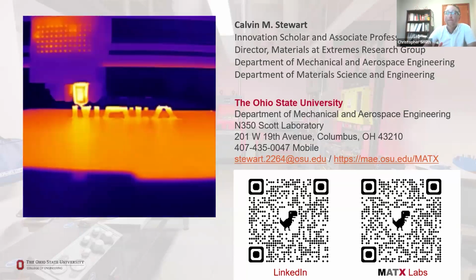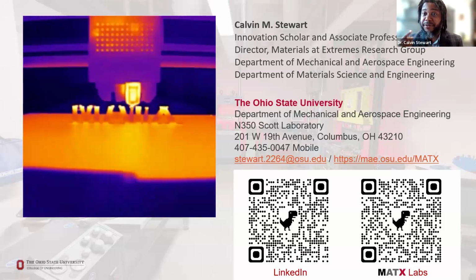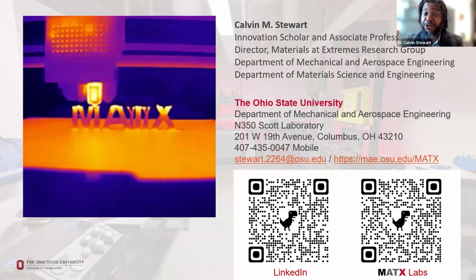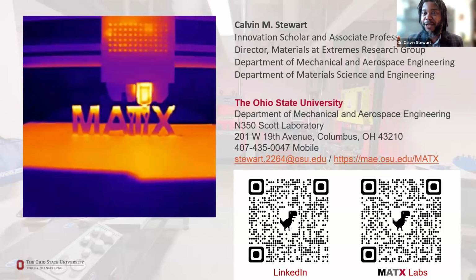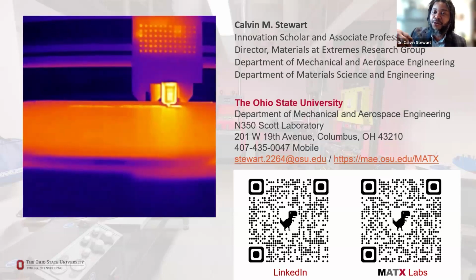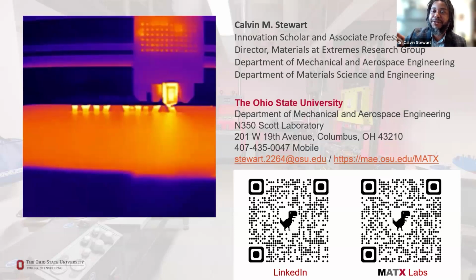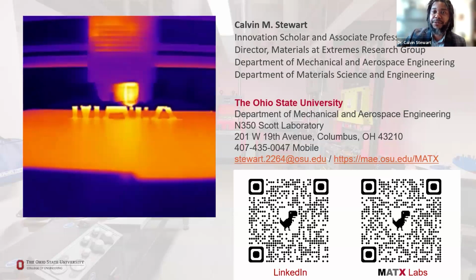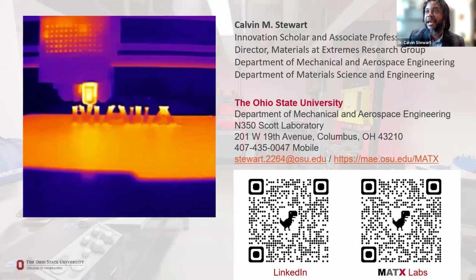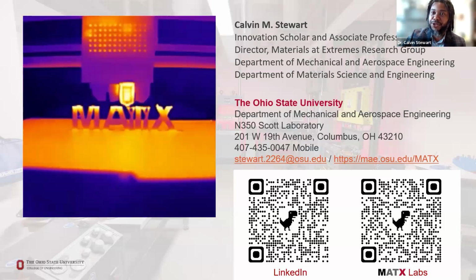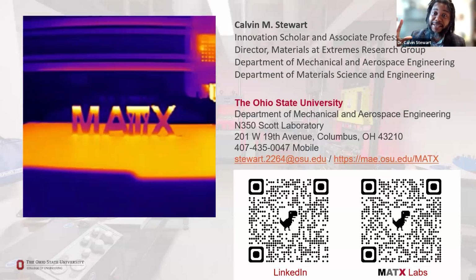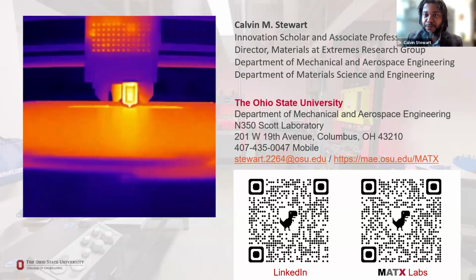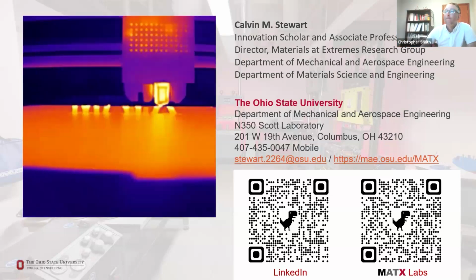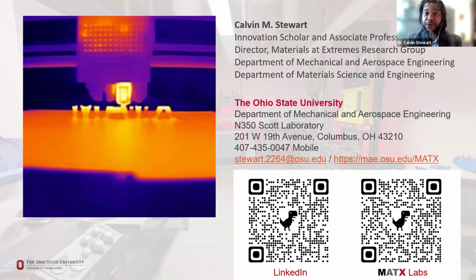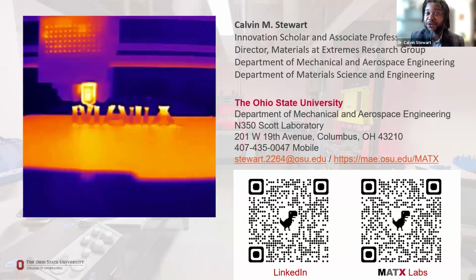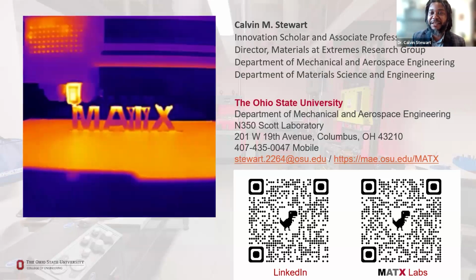They are doing laser powder bed fusion to create a copper inner liner that shields your part, that allows for heat transfer, that prevents you from melting, right? And then they're doing DED to create an outer jacket around that copper liner of something like Inconel or a high-strength steel. So they are doing a two-step process of laser powder bed fusion followed by DED to create engines that are currently going to space, right? Now, in that process, you're going from one AM step to another, and heat treatment is not possible in these steps.